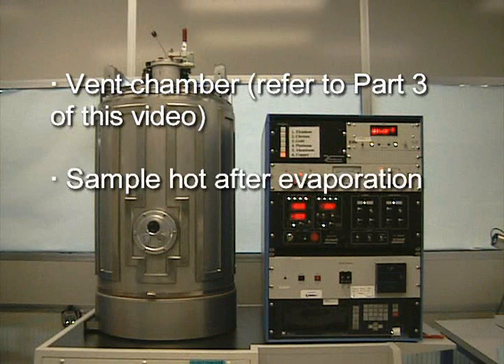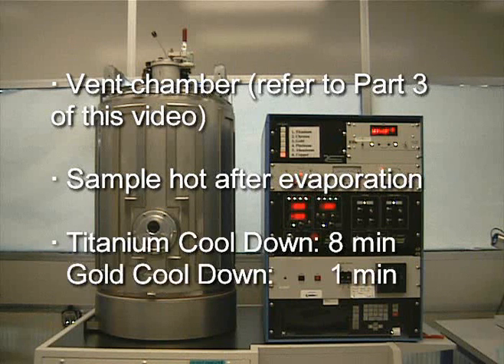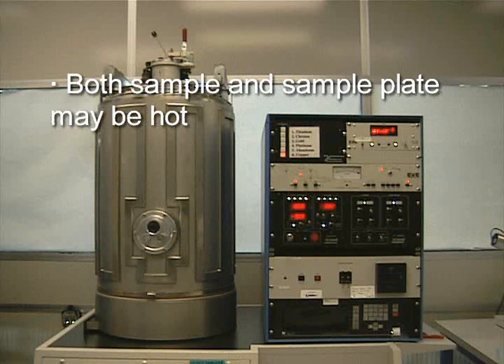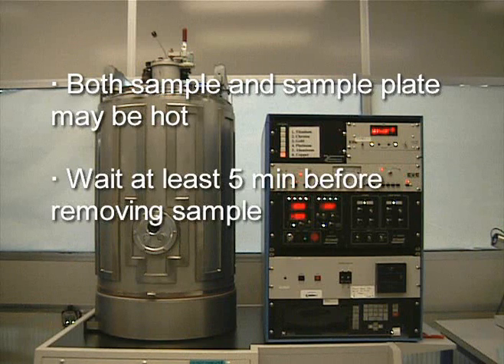After the evaporation, the sample will be hot. Give some time for the metal to cool down before taking it out. Different metals cool down at different rates. Titanium takes the longest at 8 minutes, and gold takes the shortest at just under a minute. Also remember that both the sample and the sample plate may be hot. As a general rule, wait at least 5 minutes for all metals to cool down or until the metal has stopped glowing. Please remember to be safe.